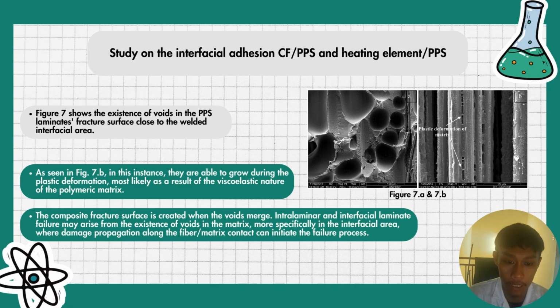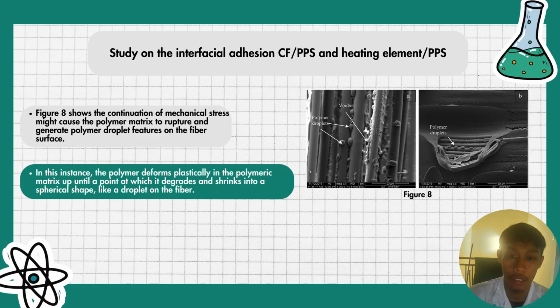The composite fracture surface is created when the voids merge. Intralaminar and interfacial laminate failure may arise from the existence of voids in the matrix, more specifically in the interfacial area, where damage propagation along the fiber matrix contact can initiate the failure process. Figure 8 shows that the continuation of mechanical stress might cause the polymer matrix to rupture and generate polymer droplet features on the fiber surface. In this instance, the polymer deforms plastically in the polymeric matrix up until a point at which it degrades and shrinks into a spherical shape like a droplet on a fiber.